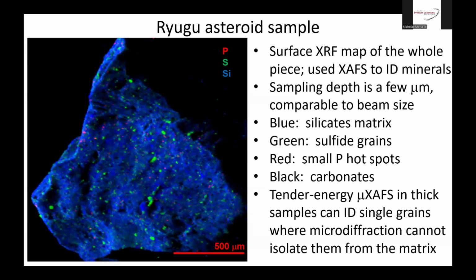It's also important to make the distinction that XAFS can identify phases of grains in samples like this that microdiffraction won't be able to resolve, because microdiffraction at harder X-ray energies will be sampling the whole thickness of a sample. So it's an advantage that spectroscopy has over diffraction in some cases.